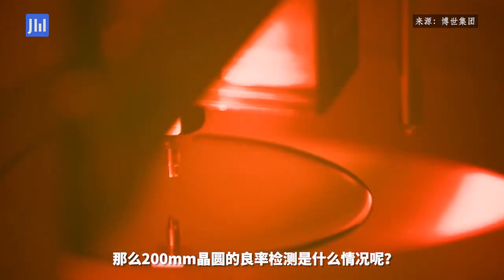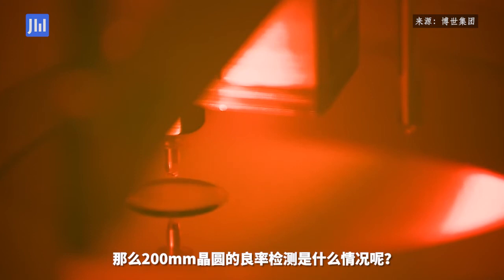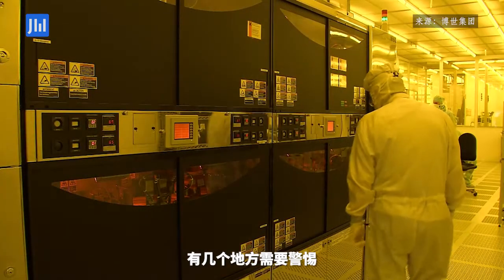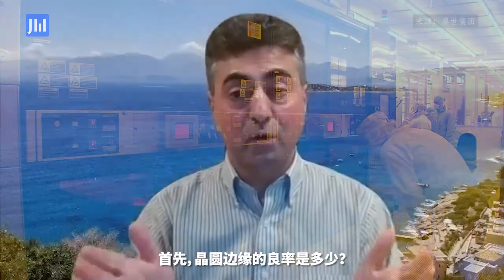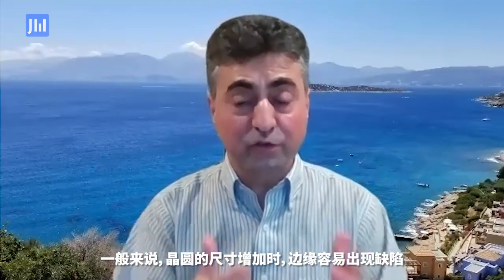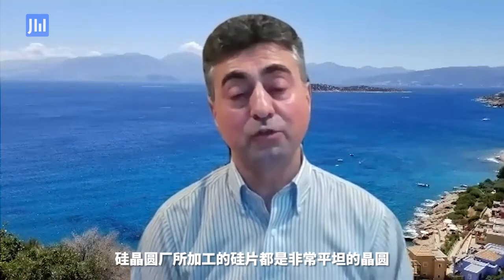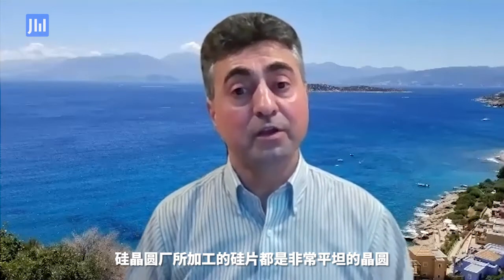So what happens now with the test, the inspection, and the yields when you get to the 200mm wafers? A couple of things you need to be vigilant about: number one, what are your yields going to be towards the edges of the wafer? Because it's usually the edges of the wafer that contain defects when you increase the size of the wafer. And the second thing is the planarity of the wafer. Even for the 150mm wafer, the planarity is really bad, so to speak, relative to that of silicon. So when you go into a silicon foundry where people are trained to have very flat wafers and do the processing, if your wafer is not very flat, that is a problem.